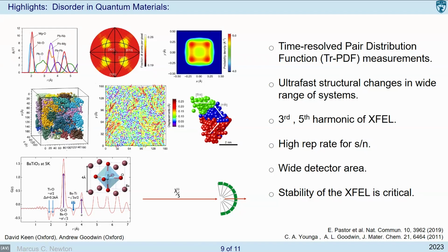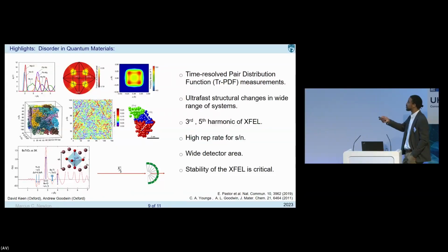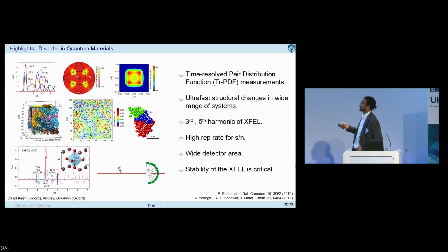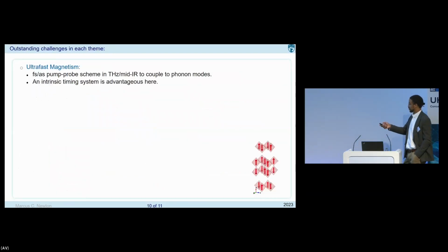having high energy X-rays, so up to or beyond 25 keV are necessary to achieve this. And we could do so using the third or fifth harmonic of an XFEL. We also require high rep rates and typically a wide area detector to capture all those different orders. So that's a challenge. And the stability of the XFEL is critical.